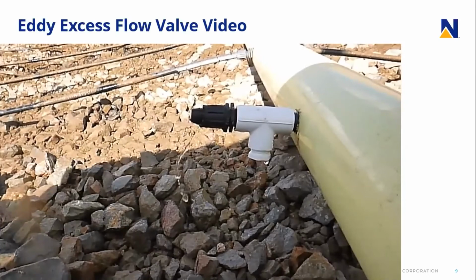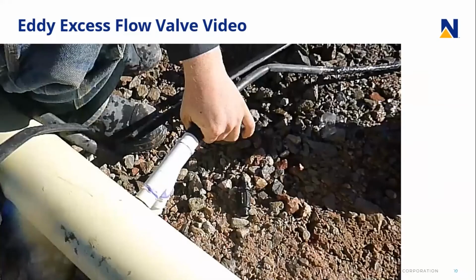As you're seeing there, the drip tube is being pulled off of the adapter. The ball in the bottom side of the T gets lifted up and quickly put into the inlet side of the adapter. This is a video of a Y-type fitting where the ball is down on the bottom side of that Y. You see the same thing with this one. It's at a lower pressure, so it takes just a split second more for the ball to lift up into it.